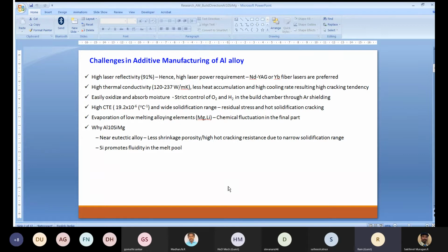And lastly, in this alloy you have magnesium, which has a lower melting point. There is a tendency for these low melting alloying elements to evaporate in the melt pool by the laser, which creates chemical fluctuation in the final part. So these are the challenges in the aluminium alloy.